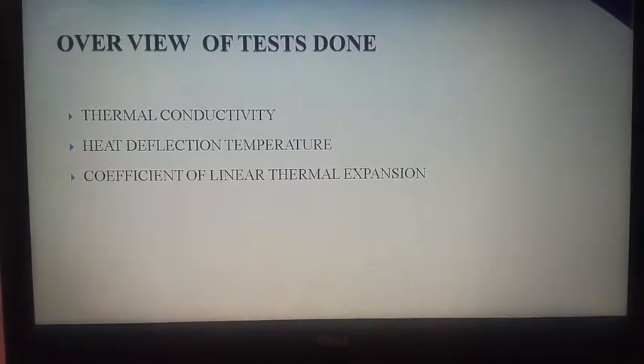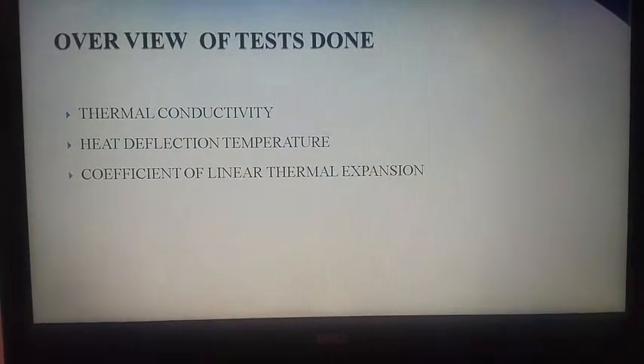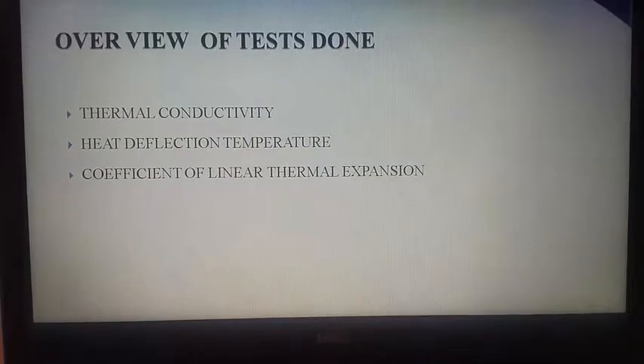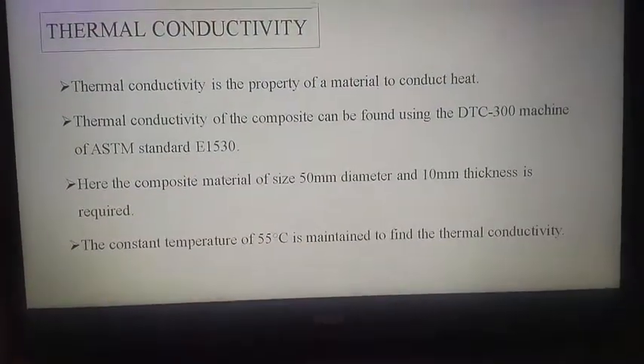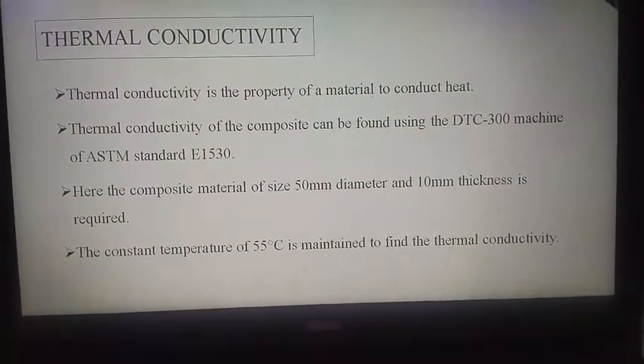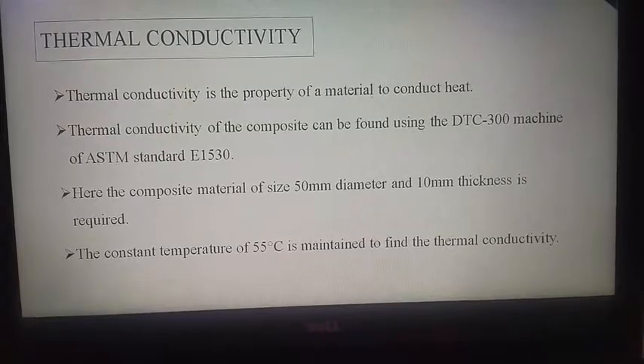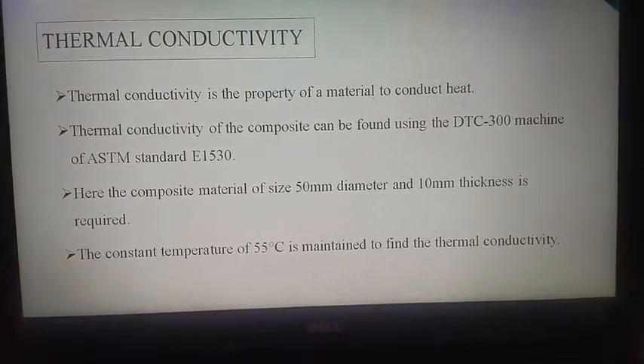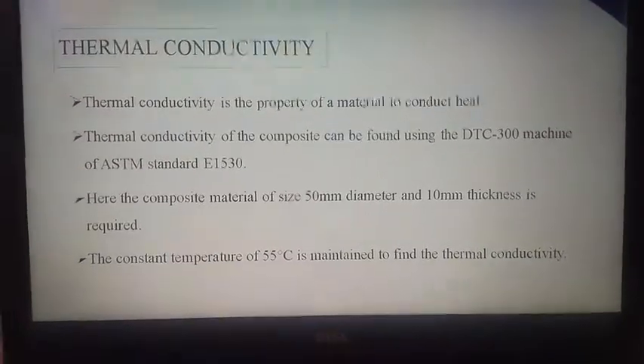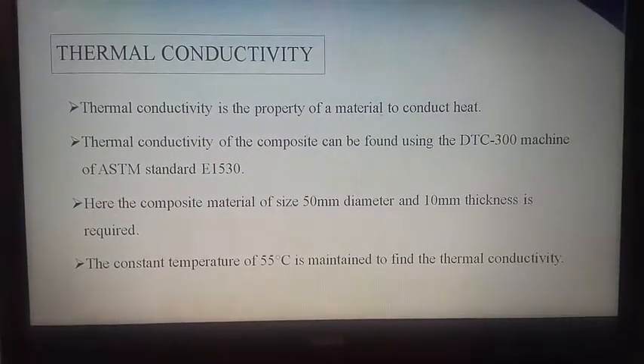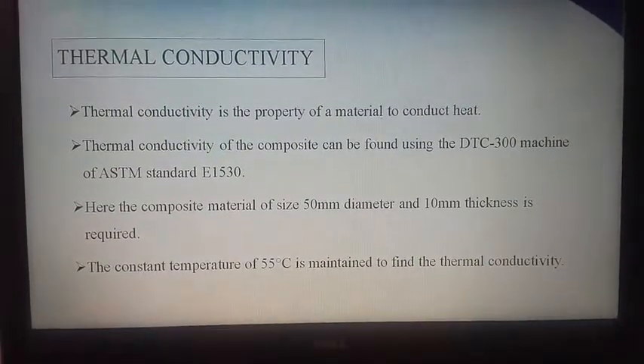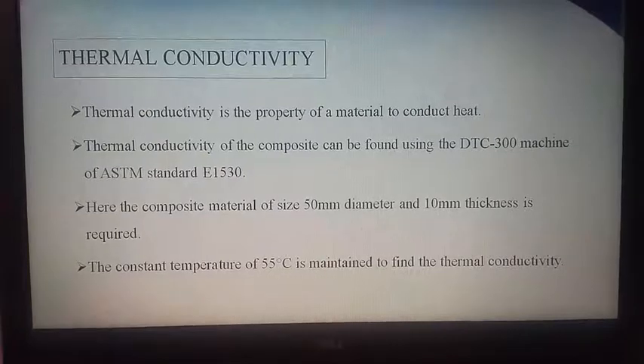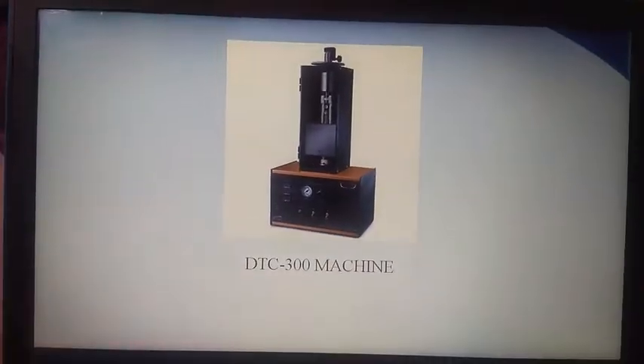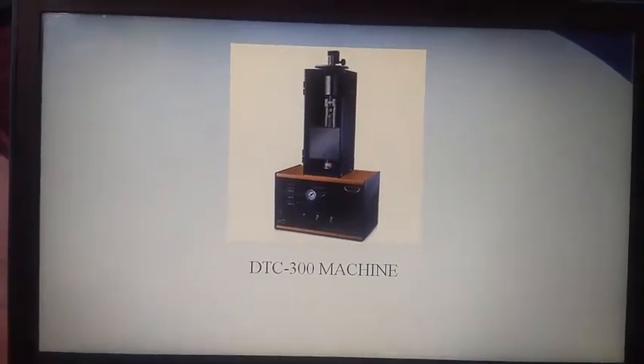This is the test we have done: thermal conductivity, heat deflection temperature, and coefficient of linear thermal expansion. Thermal conductivity is tested with a DTC 300 machine. We need a material size of 50 mm diameter and 10 mm thickness at a constant temperature of 55 degrees centigrade. This is the machine we used for studying thermal conductivity.